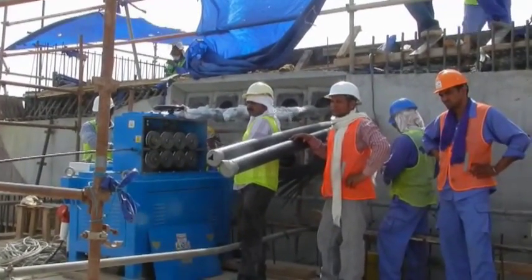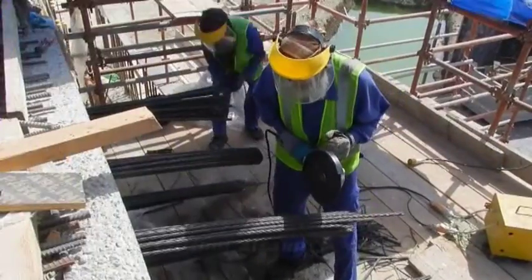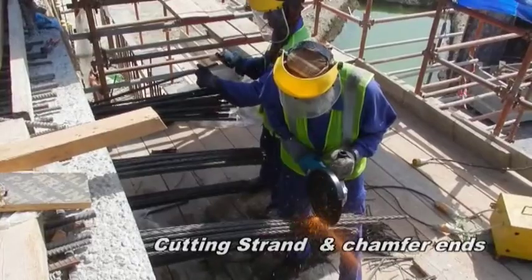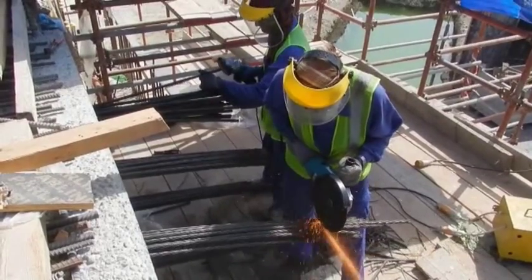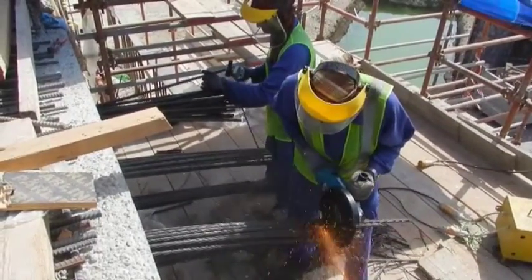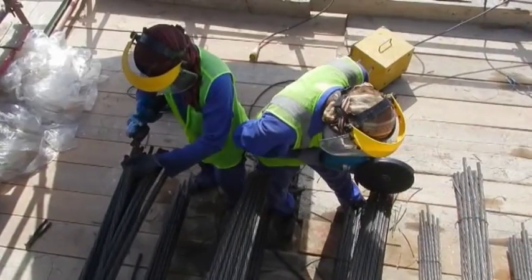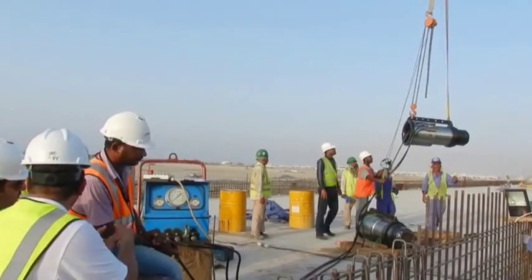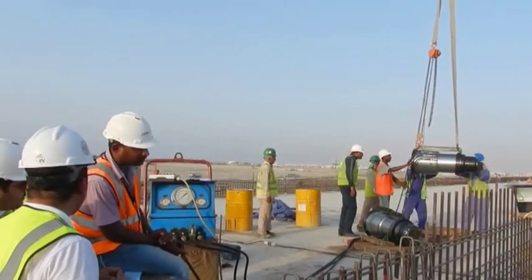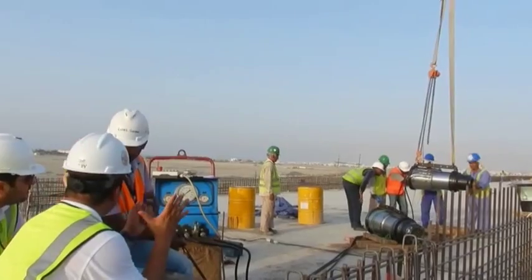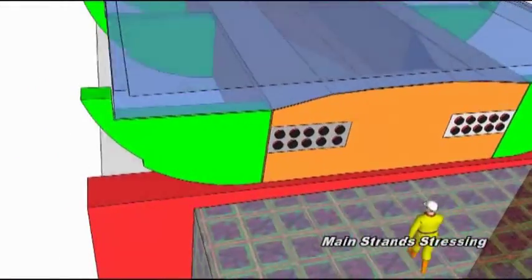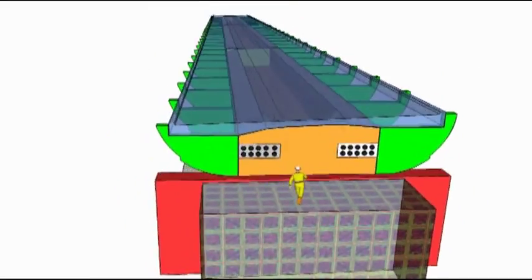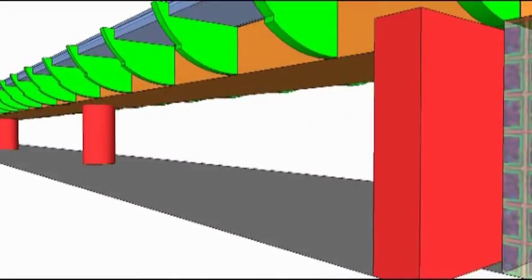Following the regulations in jack force, the stressing requires the simultaneous reading of pressure and elongation. The control of the pressure and elongation results is done by checking the comparison between these values and the theoretical ones. The grouting of tendon ducts is executed using a colloidal cement mortar. The grout is pumped until the tendon duct is filled.